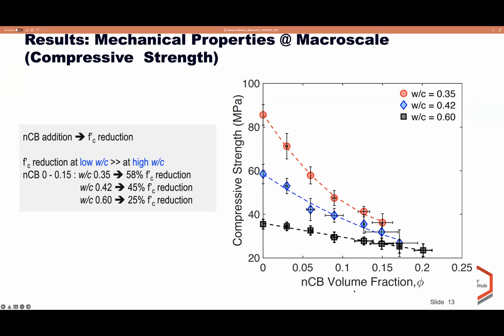What we observed here is that the addition of nanocarbon black volume fractions leads to a big reduction in the compressive strength. The second message is that the reduction of the compressive strength at low water cement ratio is higher than at high water cement ratio. For example, at 15% nanocarbon black volume fraction, the reduction of the strength at water cement ratio 0.6 is about 25%, while the reduction for water cement ratio 0.35 was up to 60%.